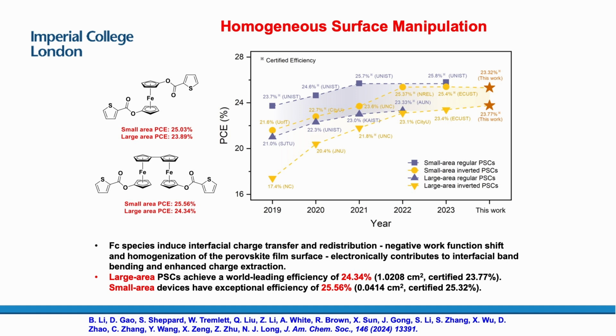It's very small relatively, but the small area devices is where the field has currently shown, but actually scaling it up from 0.1 centimeter to 1 centimeter is quite difficult at the moment. But we're able to do that with our collaborators and still retain the efficiency that we had. So this again really reinforced the initial publication and shows that this is actually transferable to other devices.